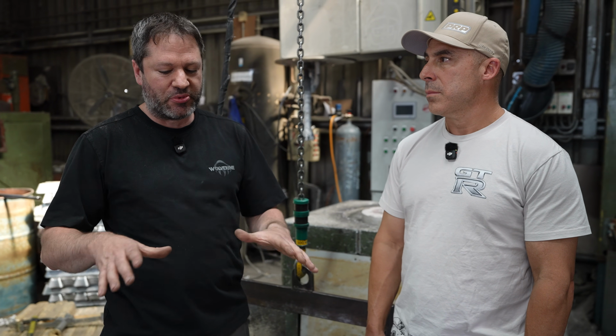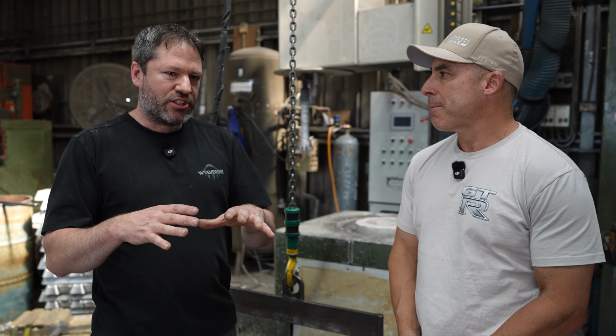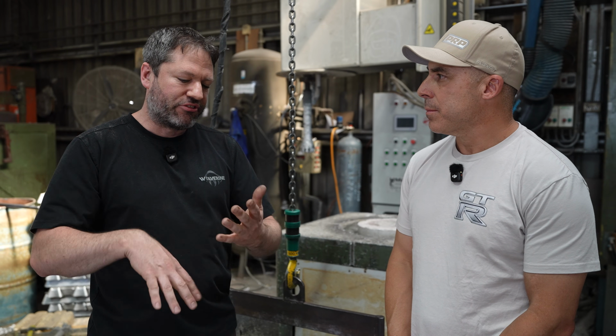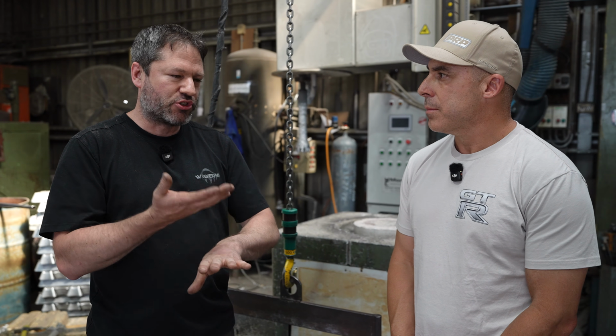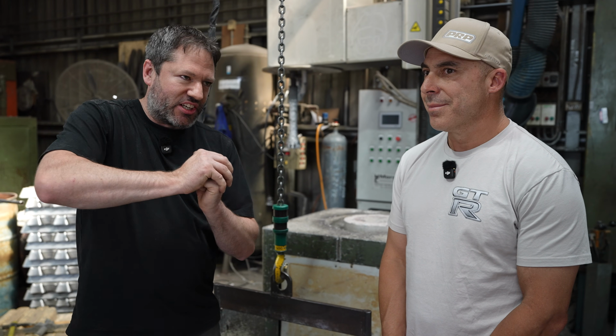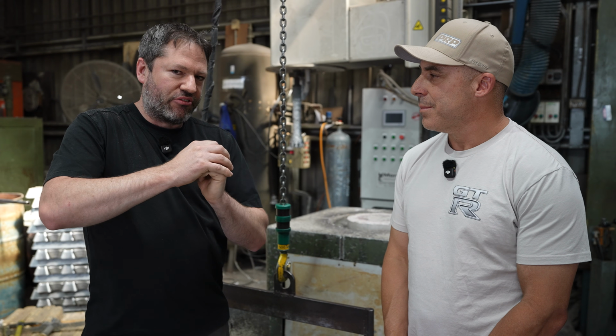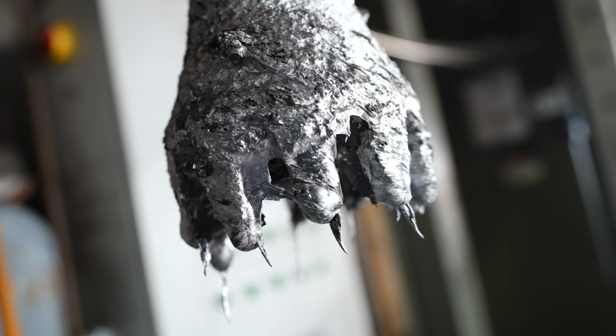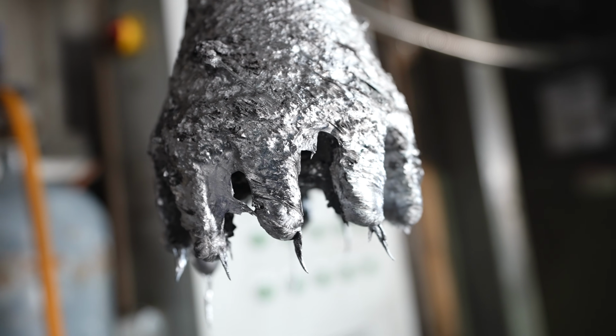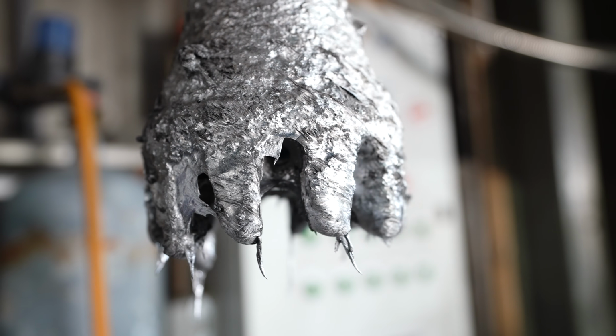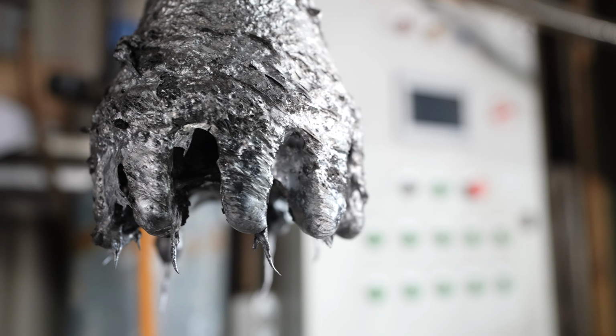from the bath. So oxide films form on molten aluminium almost immediately. So when you see aluminium in the molten state, you've got this film on top, which is like a dry ceramic. And if you've got turbulent metal and it folds over on itself, you get a dry side to dry side, and you get a trapped entrained pocket of air in there. Yep. And then the head pressure of the metal after you pour it holds that shut. But once it starts to solidify, it's free to open because that head pressure's not there. So you've got to get those films out, and the best way to do it is with nitrogen degassing on a system like this. You get porosity and cracks. Exactly. You're basically pouring porosity and cracks into the casting if you don't clean out the oxide films first.